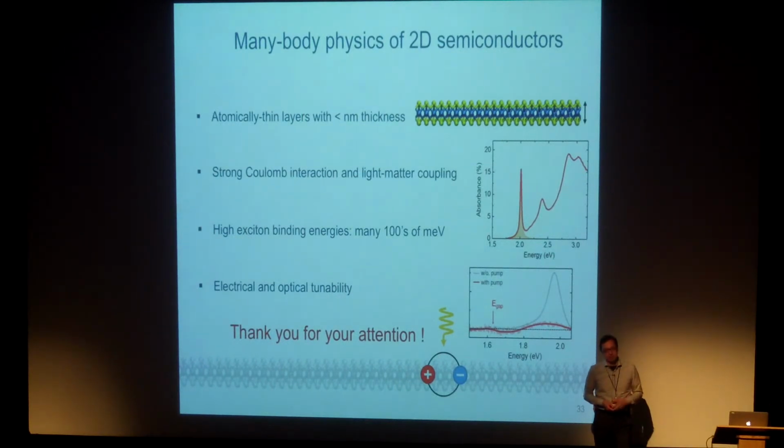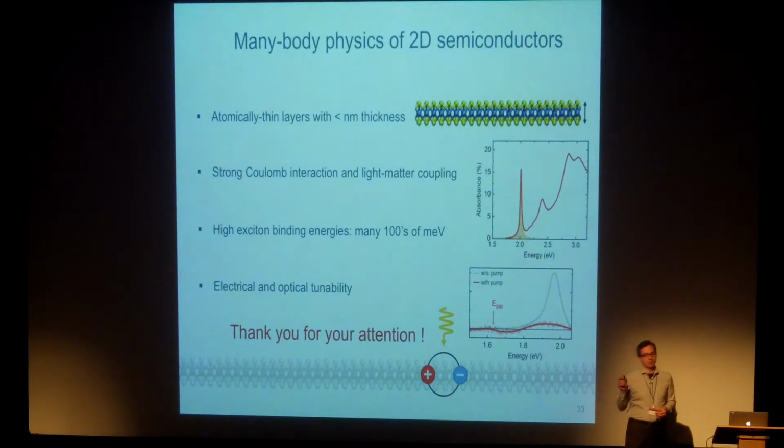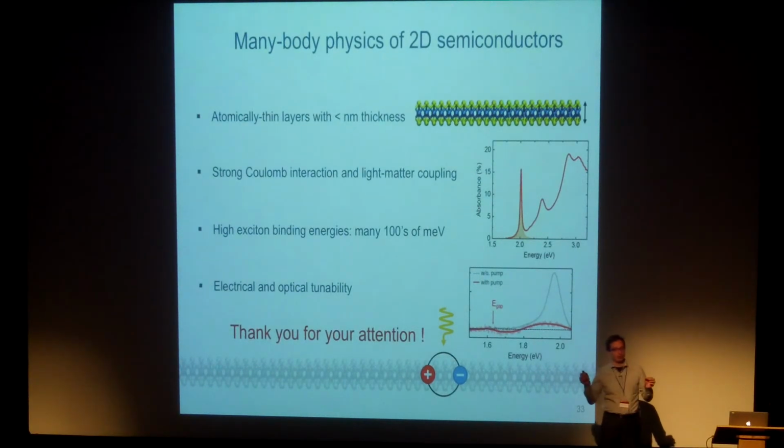A separate question related to that, however. If you're just in the direct regime, how well nested are the electron hole Fermi surfaces? Are they pretty cylindrical? They are so close to the minima. They are roughly cylindrical, but the further you go away, you start to see the implication of the hexagonal structure, and they have sort of mass anisotropy and things like this because of the symmetry. But that barely affects the region where we have our exciton wave functions.